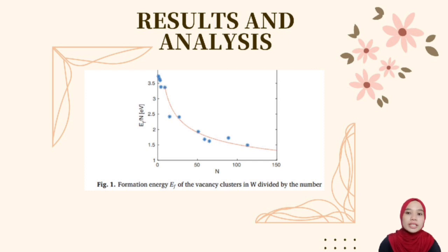The scatter of formation energy is probably mainly caused by the random phasing introduced by intersecting the sphere with the BCC lattice. Indeed, in reality, the void surface will be faceted preferentially by {110} planes, where the surface energy exhibits a minimum. Other factors explaining the scatter include the incoherent edge between phases.